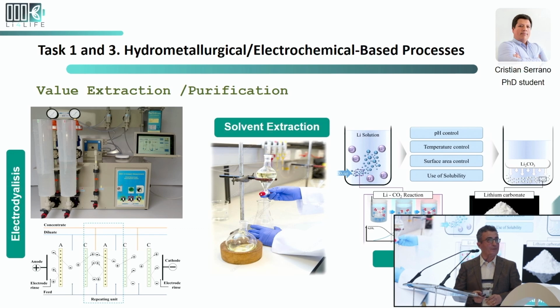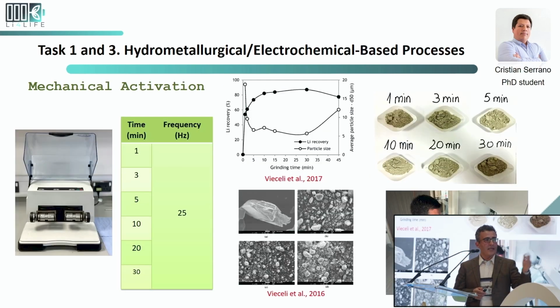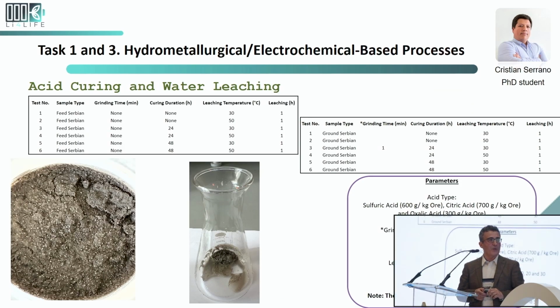And these are a couple of the results through our mechanical activation, and the idea is we try to weaken specifically the clay and silicate phases, which would favor the leaching process, and we're hoping we will reduce the energy use compared to the normal thermal processes.